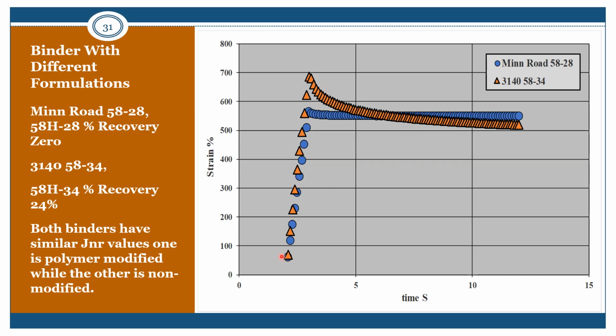So in the 5828, you load that binder, it deflects, but now it's primarily in the viscous mode, which is what we expect based on all the grading we've done. And so now there's no recovery. It deflects, and it stays in the same location. And so we have the same rut resistance for these two materials, but very different cracking or durability responses.